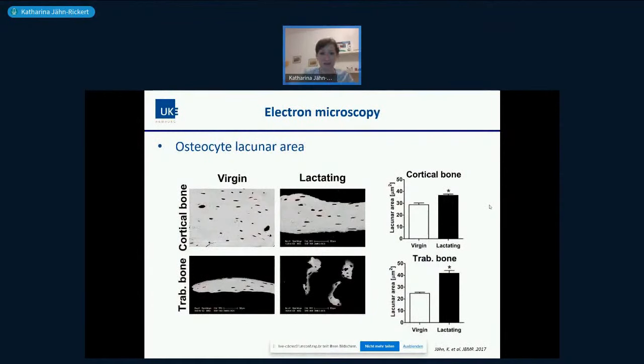Coming now to electron microscopy, something that we looked at quite a lot when I was in the US, where we looked at the effect of lactation on osteocytic bone remodeling. So while you have heard that osteoclasts are the bone resorbing cells, there was some older literature that also indicated that osteocytes inside the lacuna can also resorb matrix, so the perilacunar matrix, and therefore the osteocyte lacuna should be getting bigger. So we looked at mice that were breastfeeding, so lactating, and we found that in the cortical, but also especially in the trabecular bone, these lacunae were enlarging compared to the virgin mice, that never had pups before, and one could quantify this with lacuna area.